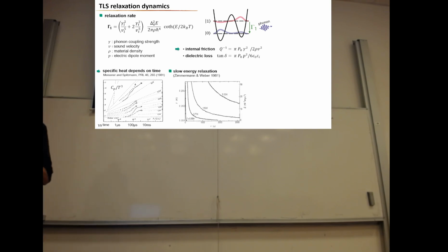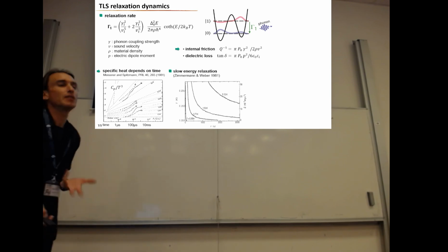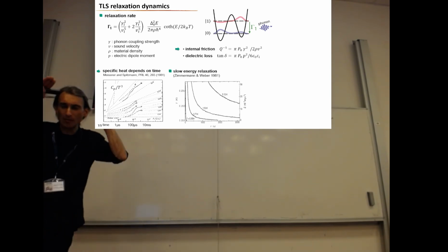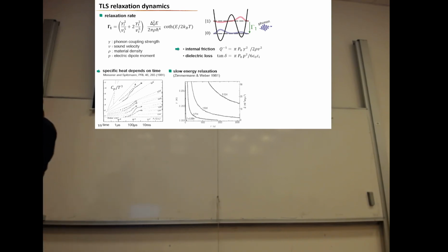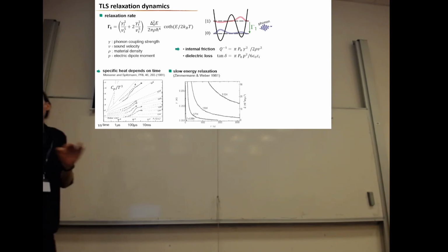The other thing is that it's actually difficult to cool down these amorphous materials. People recognized that after they started the cryostat, it can take rather a long time until the sample really equilibrated and got cold. And this is again just the effect of these relaxation rates, which I have to say are also widely distributed. I mean, each TLS is different, right?